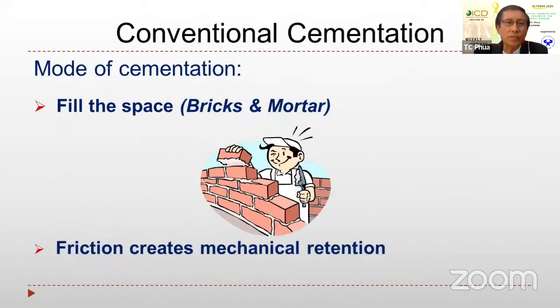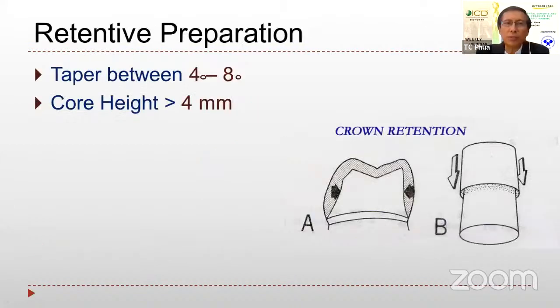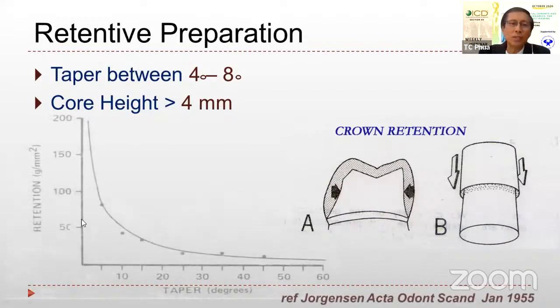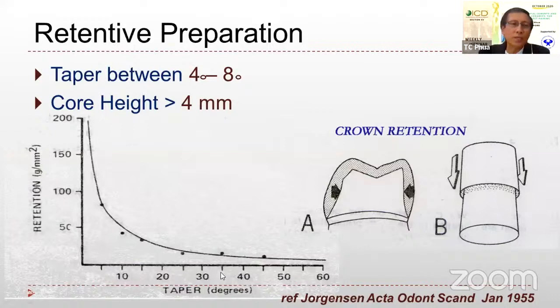So conventional cementation works essentially to fill the space, and the friction creates mechanical retention. So it's a bricks and mortar type of situation where you're filling in the space. And retentive preparation is very much required. If you remember our time in dental school, the preparation should have a taper of anything from 4 degrees to 8 degrees. You find that if you go beyond 8 degrees, the amount of retention drops off remarkably. You need to have a core height of 4 millimeters to resist the loss of retention. And from the early studies of Jorgensen, you find that somewhere beyond 8 degrees, the rate of retention drops down remarkably.